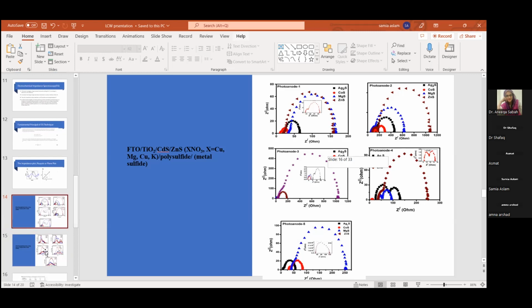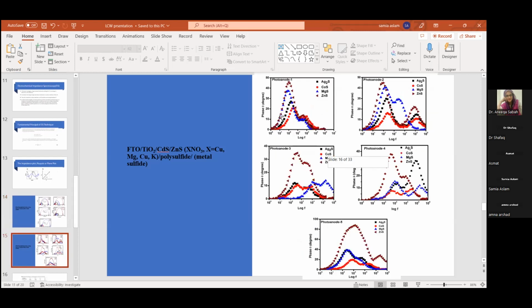Right. So this is also represented by Bode plots, which is the frequency with respect to the impedance. Any parameter plotted as a function of frequency is represented by the Bode plot in EIS analysis. And here, clearly we can see the resonance frequency curve. Here I've represented it with a phase, and the resonance frequency tells us the relaxation mechanism, that for how much time the charge remained live in the device.